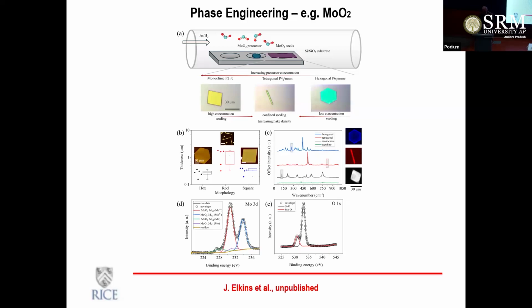It's not necessarily the dichalcogenides, but also dioxides, things like molybdenum dioxide can exist in multiple phases. It can be metallic, it can be semiconducting. So when you grow these materials, you have to worry about how you can control specific type of phases. The reason why I just showed you is because later on, I'll talk about some lateral junctions, heterostructures, where this phase engineering is also quite important.